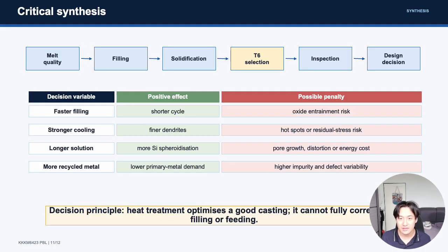The critical synthesis is that no single step should be optimized alone. A faster filling may improve the productivity, but increase the oxide entrainment. Longer solution treatment may improve the silicon morphology, but increases the pore growth risk. More recycled material improves the sustainability but can increase the impurity and reliability risk. So the best decision is to integrate the chain: the melt quality, filling, solidification, T6, inspection, and the defect-sensitive design.